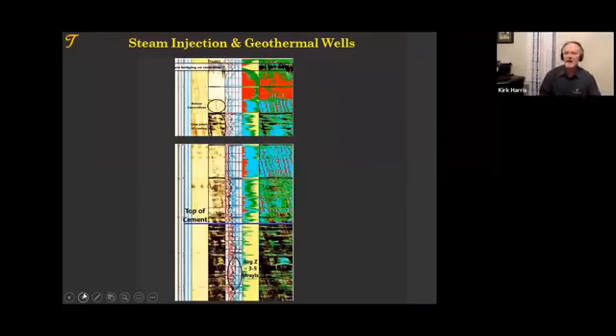I want to point this out as far as steam injection or geothermal wells. Here's a big problem. It's in deep water wells this occurs as well. You cement the well and you have losses, and so you do not get cement to surface. For a geothermal or a steam injection well, you want it to surface. What do you do at that point? What do you do if you have losses and the losses are low, or you feel your weak zone is quite low and you have total losses?